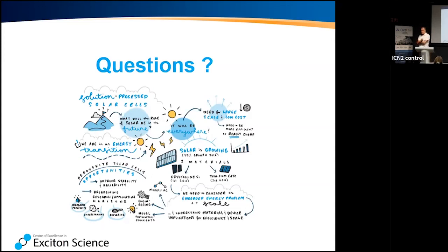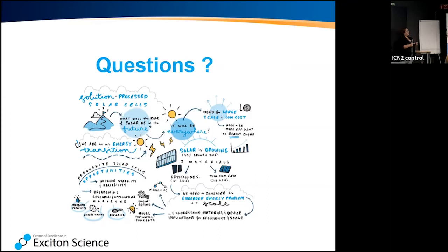But I know there's a huge controversy, there's people who do experiments. They say, look at my experiments, it clearly shows that it's ferroelectric, and there are other groups that contradict that. The fact that we have twins is kind of pushing towards the fact that it should be ferroelectric. Yes. It's hard to measure because of the properties of the material. I think one thing that's definitely in your way is the ion mobility. As soon as you apply strong electric fields to your perovskite, your ions are just going to move all over the place, and that obviously gives you a polarization signal when you do that. It's very challenging.